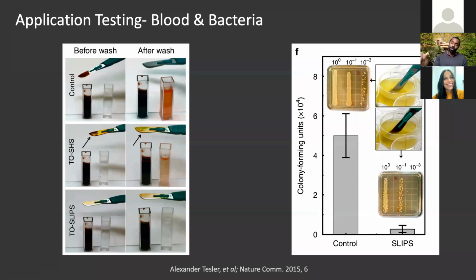So this may be useful in just keeping objects clean, and maybe also against bacteria. Here we incubated these treated scalpels in a broth of culture medium with Staph aureus, something that's very medically relevant. And we see about a 5x reduction in adhesion to the slippery surfaces compared to the control surfaces. This is a really high concentration exposure, but we can start to get some biological resistance through this design strategy.